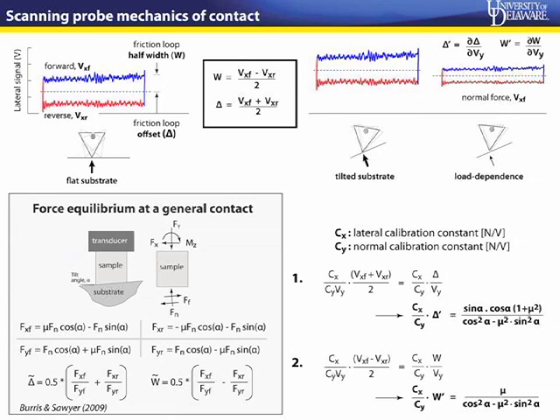And if you're changing load, you're also changing the amount of that initial moment that we talked about that you're applying. So you essentially get a load dependence of both delta and W on a tilted substrate. Now, if you look at the case of a general contact, the force equilibrium of a general contact and sliding system where you have the substrate, you have the transducer, and you have some sort of a tilt angle between the substrate and the transducer.